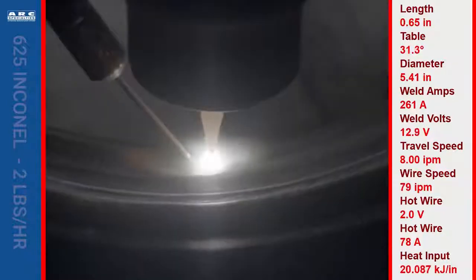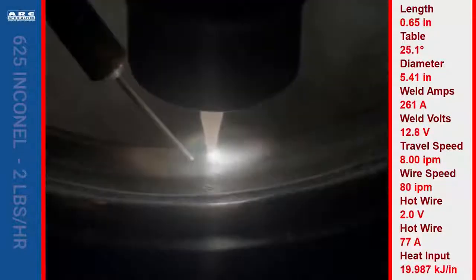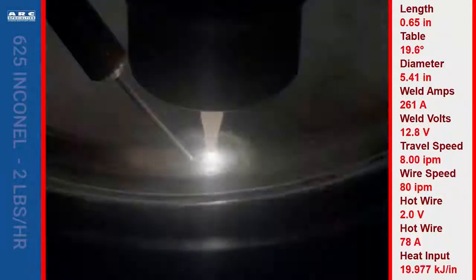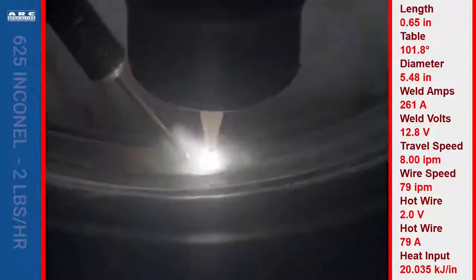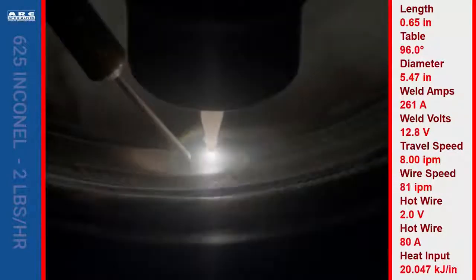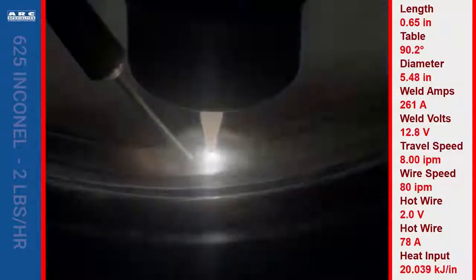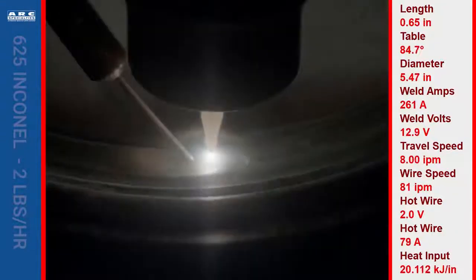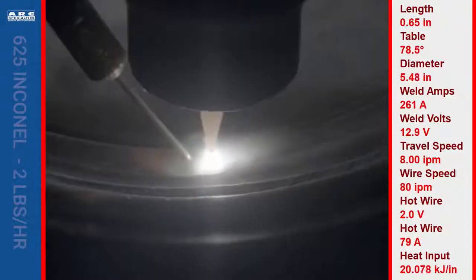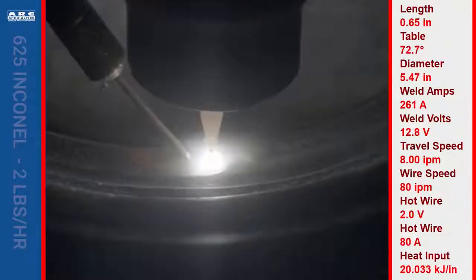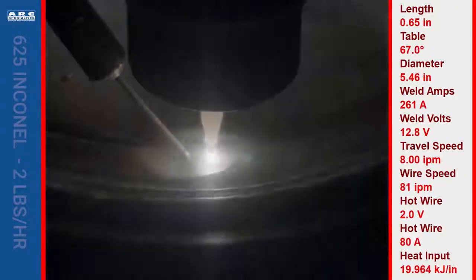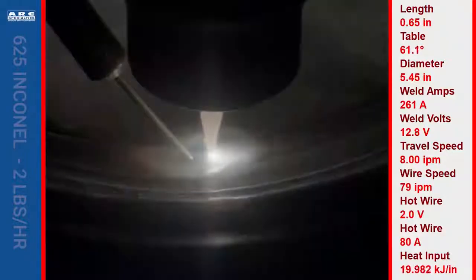I've seen people running too many arc volts and then misinterpret the melting of the wire as excessive hot wire volts. This is not the case. You're simply running the wire at the wrong position in the puddle. So that's a key variable you need to adjust, is arc voltage, to ensure that the wire is impinging back in the puddle a bit away from the arc itself.